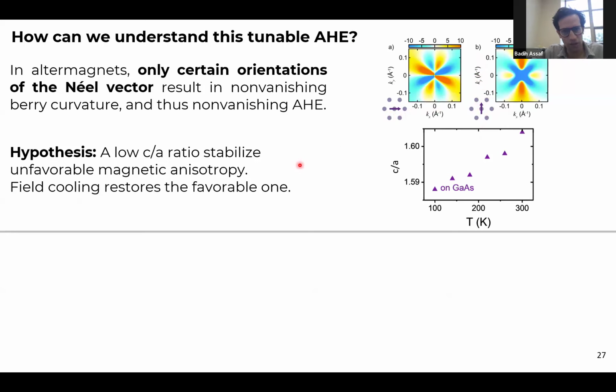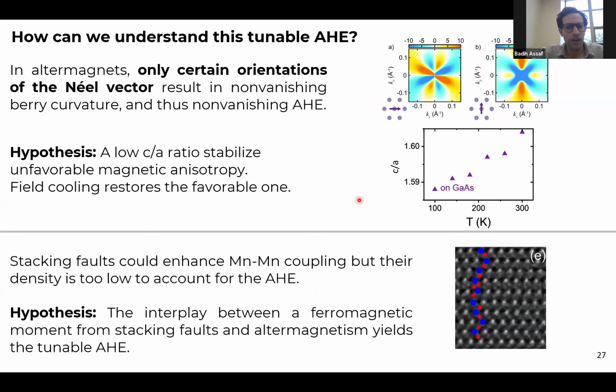So it's possible that the strain is actually favoring this direction, and then by field cooling, we retrain the material to orient its easy axis along the Y direction. Field cooling will essentially change the Zeeman energy in your free energy landscape and could stabilize one anisotropy versus the other. Another hypothesis is that stacking faults actually alter the manganese-manganese coupling locally.